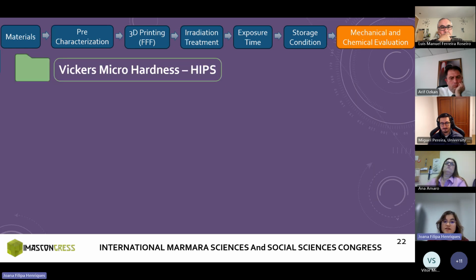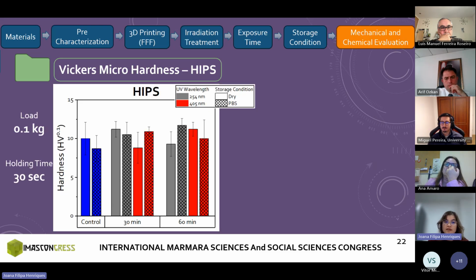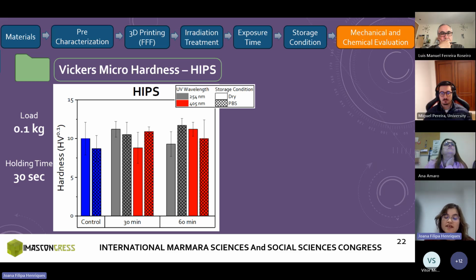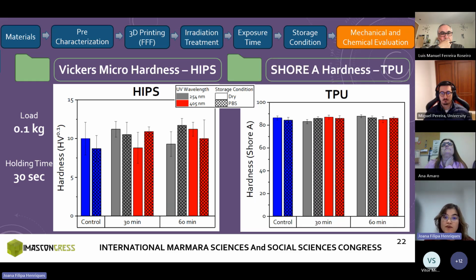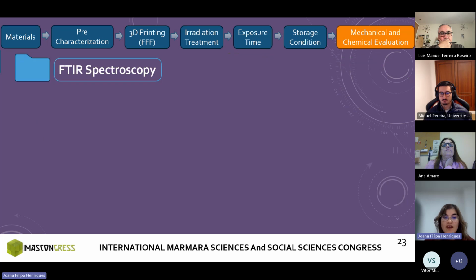Then we measured the hardness of specimens. And since the materials have completely different behaviors, we had to use two different measuring methods. For HIPS, we used Vickers microhardness, and the results did not present significant differences. For TPU, we used Shore A hardness, and once again, the results are not different amongst the treatment conditions.